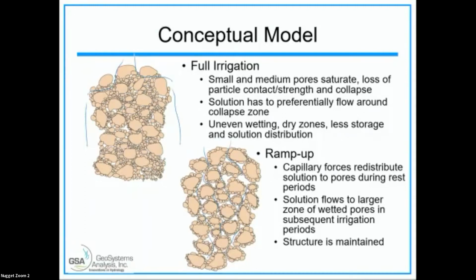this is the thing about unsaturated hydraulic conductivity. It's a function of the water content. So if you have a very dry material, it is not going to be able to carry water as fast as a material that's more wet. And so as you pull that water in, you're increasing the hydraulic conductivity of your leach ore. And so the next time you irrigate for an hour, you get a bigger bulb. And then the next time you get a bigger bulb. And so you get much better solution distribution with the ramp up. And you maintain the ore structure as well.